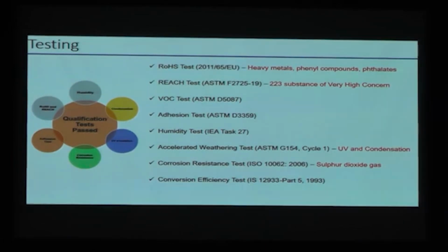This test has been done at TUV Rheinland, and they have certified that the coatings are RoHS and REACH compliant. The RoHS test clearly shows that there are no heavy metals, phenyl compounds, and phthalates present in the coating. Whereas the REACH test is very crucial. It has 223 substances of very high concern. Even if you simply use acetone in the coating, it will not qualify the REACH test. So it clearly shows that we have mainly used inorganic materials to get this technology. As I mentioned before, we have used mainly water as a solvent. So this coating has qualified the VOC test.